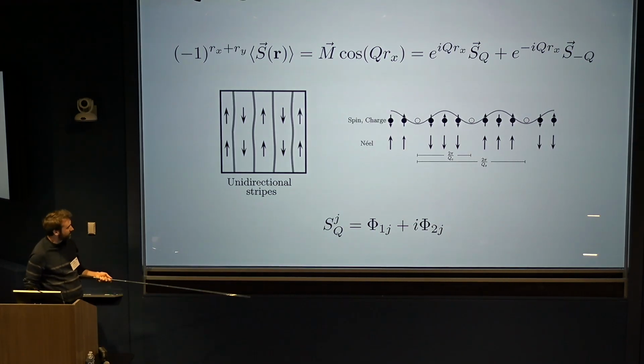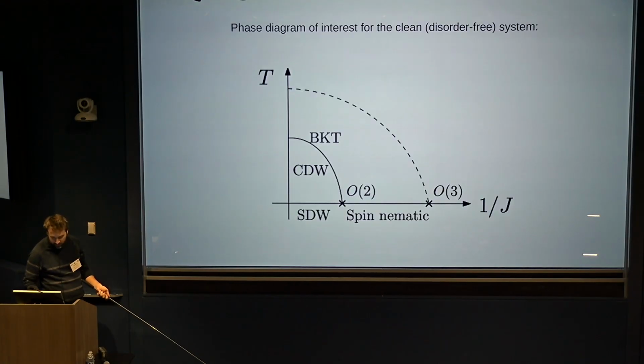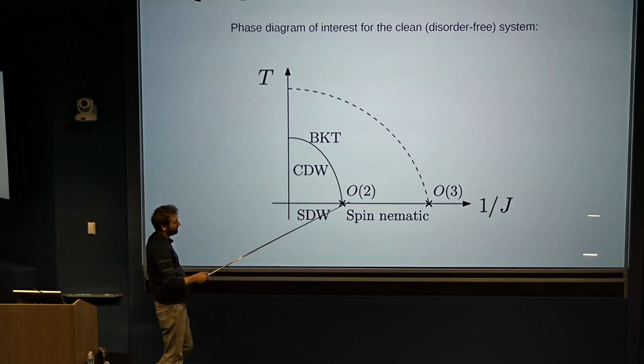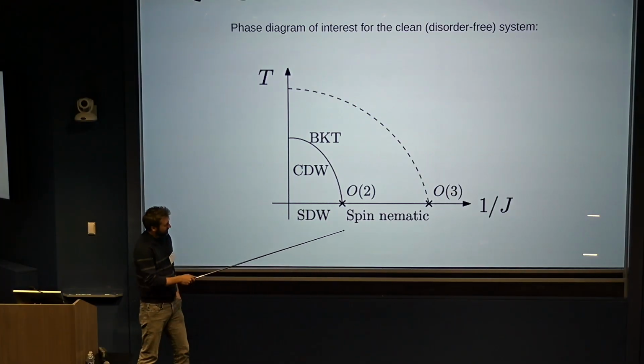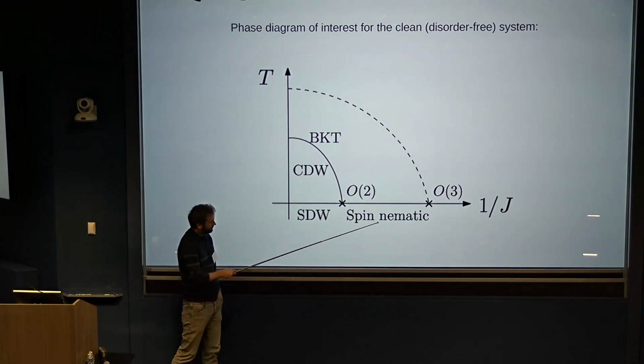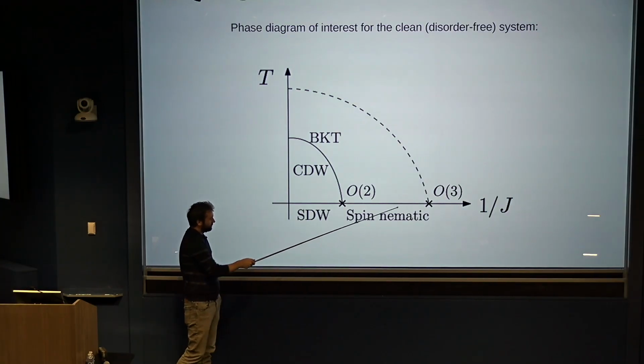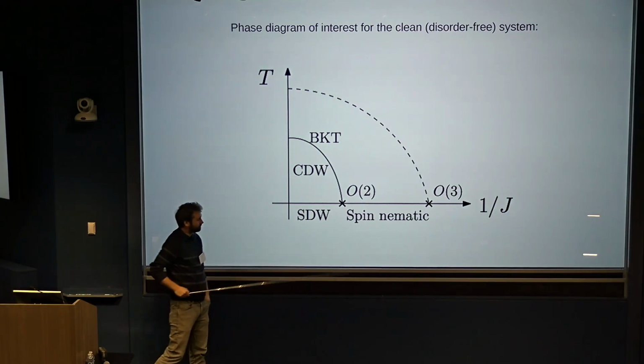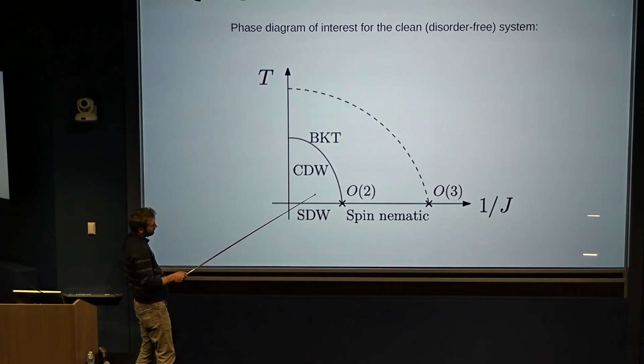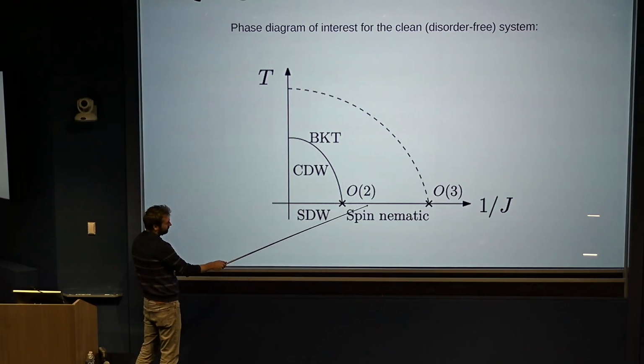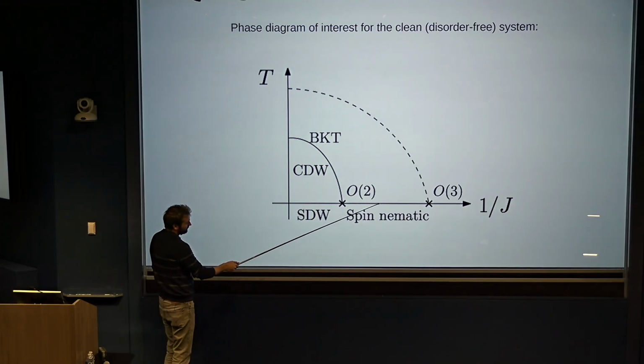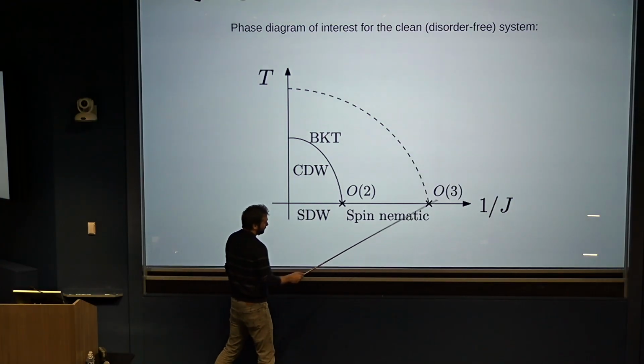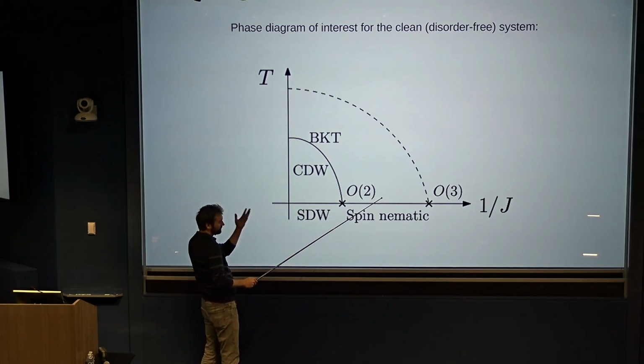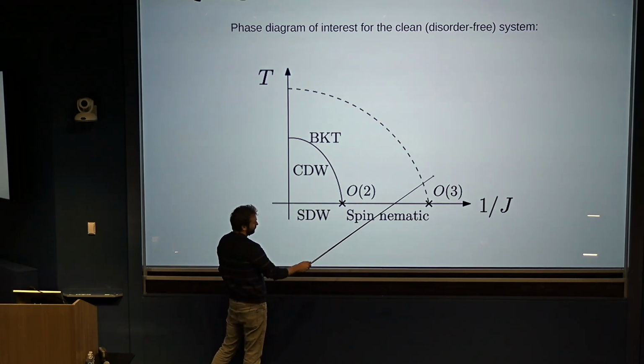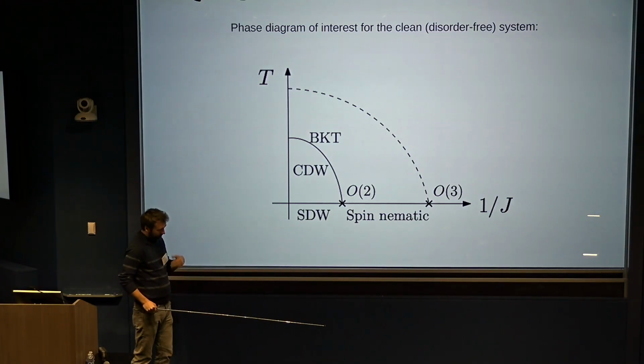So the magnetism is gone, because the direction of the spins will be disordered. But the spins do remember that there is a fixed axis in the system. So there is a preferred axis, but still there's no magnetism, and those are the properties of a spin-nematic order. So by first disordering the charge degrees of freedom, or the phason of the charge density wave order, you go from the spin stripe to the spin-nematic. And as you then further decrease the stiffness, the system also forgets about the fixed axis, and you go to a completely symmetric state.